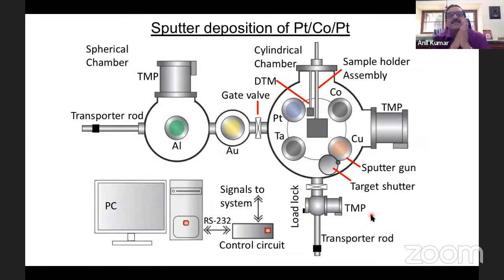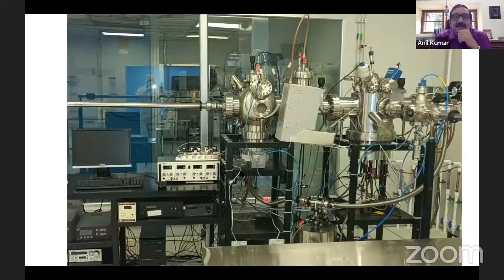We make all these films, for example platinum, cobalt, platinum, which is heavy metal, ferromagnet, heavy metal, by sputter deposition. This is a homemade ultra high vacuum sputter deposition system, which has multiple targets associated with it, and you have efficient pumping stations. This is the equipment designed by us and made in-house. And this is in a class 1000 clean room. You have all the sputtering guns here. You load the sample through a load lock.